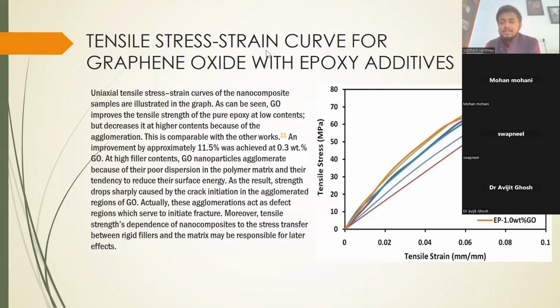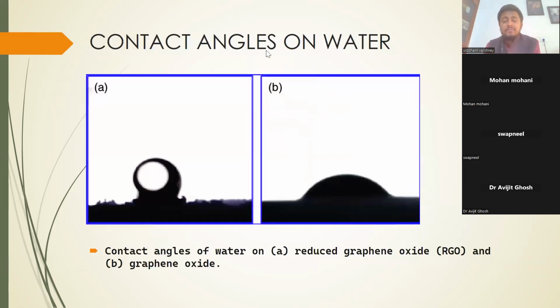How it affects is basically, and this is just 0.1 weight%, 0.3 weight%. It's reducing its elongation at break, making it more brittle, but also the tensile modulus increases. And if you have different kinds of functionality in the graphene, then you can play around with the tensile modulus and the flexibility both. But the tensile modulus is bound to increase. This is the thumb rule.